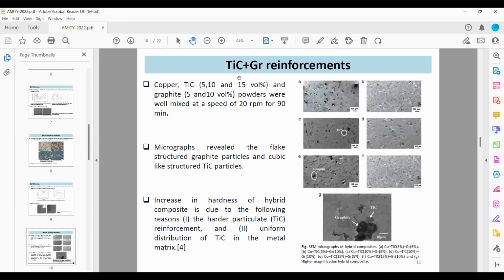Now, titanium carbide plus graphite reinforcements. Here we see that there is uniform distribution and absence of cracks, and there is strong interfacial contact between the matrix and reinforcements. These graphite flakes are present along with titanium carbide structures.